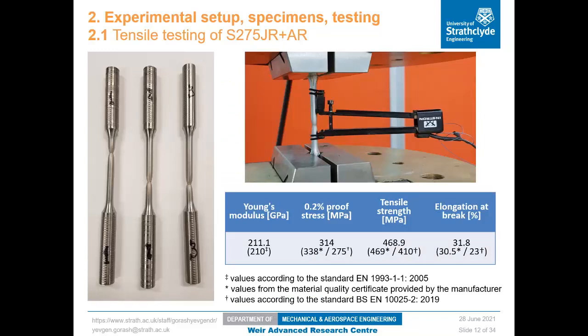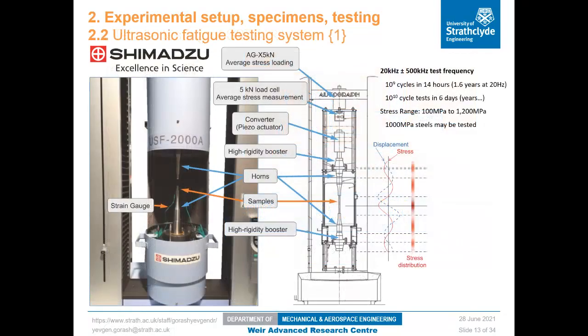Tensile testing has been done using an Instron 8802 servo-hydraulic testing machine, and the material properties such as Young's modulus, yield strength, UTS and elongation at break obtained in this testing were quite close to the values reported in the steel quality certificate. And it should be noted that such properties as yield and tensile strength and elongation at break were much higher than those required by the standard. The central piece of equipment is the ultrasonic fatigue testing system VHCF8 from Shimadzu.